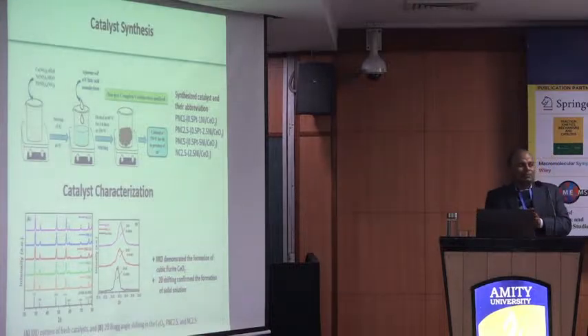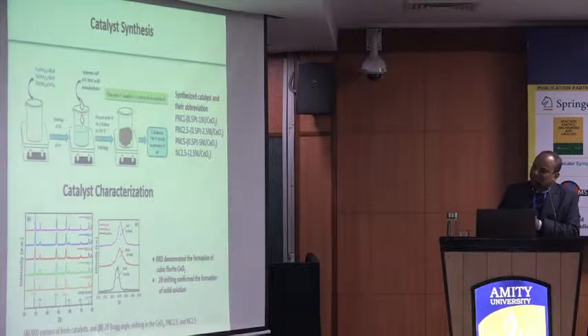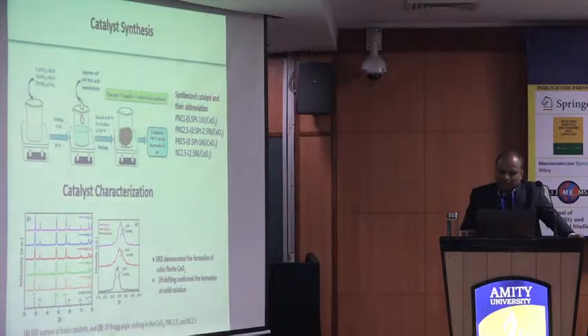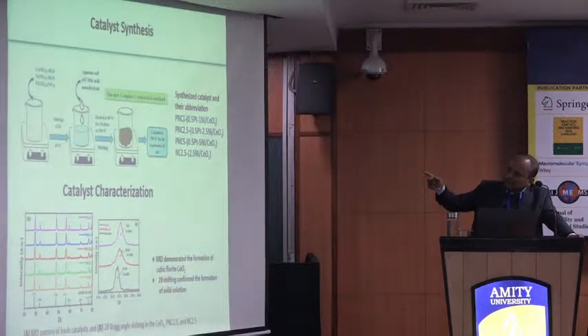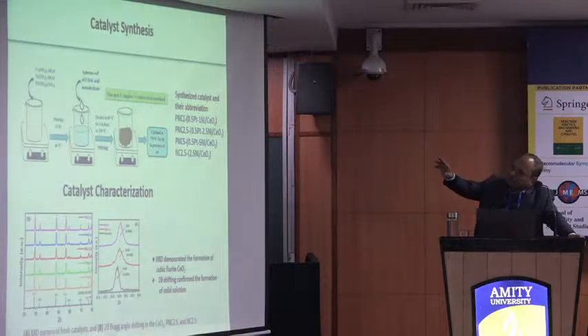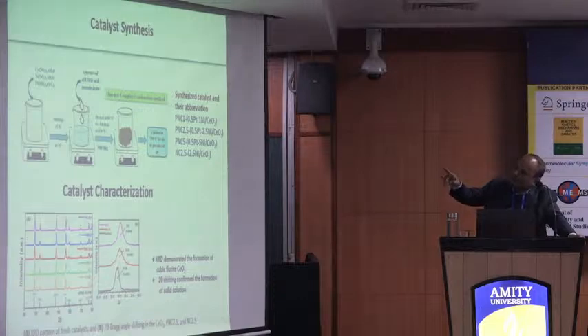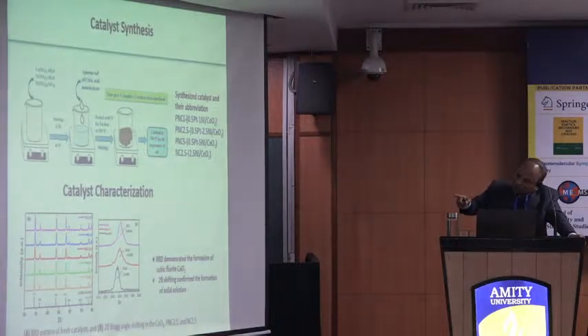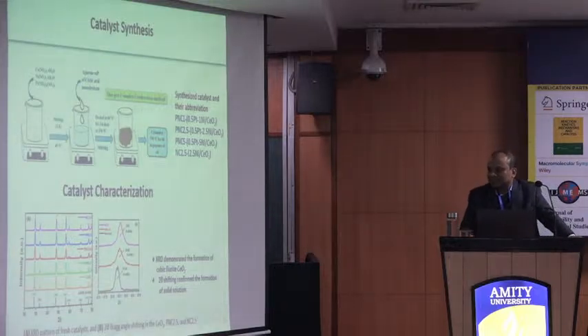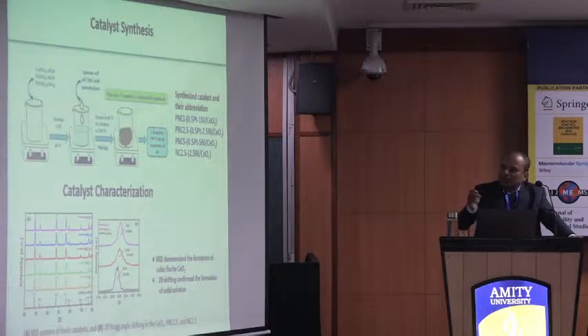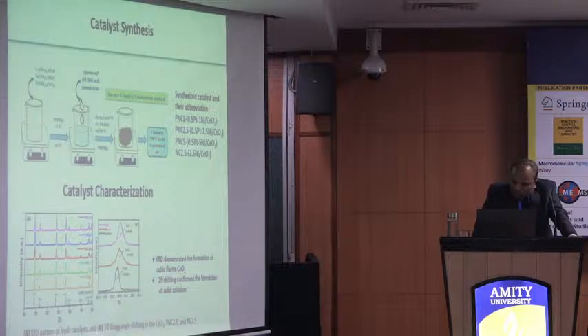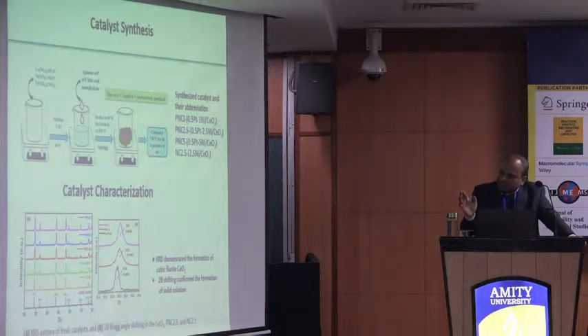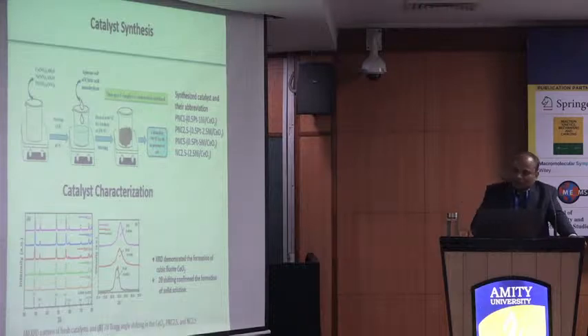In catalysis, the preparation of a highly stable and also active catalyst is challenging. We prepared the catalyst via a solvothermal method, including oxalic acid. We are using different nickel loadings, 1%, 2.5%, and 5%, but for platinum we are using a very small amount, 0.5%. This is the XRD here. It mostly shows the fluorite structure of ceria. That means platinum and nickel are very small and cannot be detected by XRD. Here also, if you look closely at the XRD peak around 28, you can see that the peak is broadening. At the same time, the peak is shifted. That means platinum and nickel are incorporated in the ceria lattice.